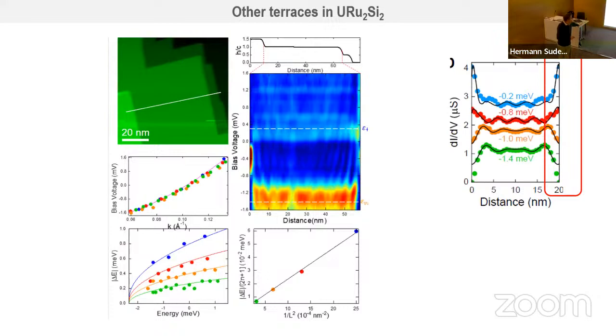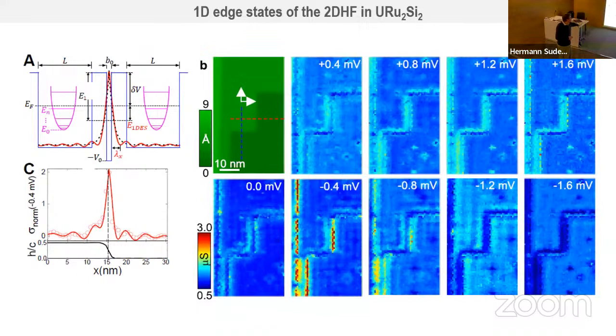Now let me show what happens here, or maybe on the borders. You see here that there is a kind of deviation of this tunneling conductance. When you take a closer look, here, this is the border of a terrace. You see that the gap opens here, and I think you may know about this from surface physics. When you have a two-dimensional electron gas and you get into a step, then you often open a gap there. And inside the gap, you may have one electronic state, which is a one-dimensional state in this case.